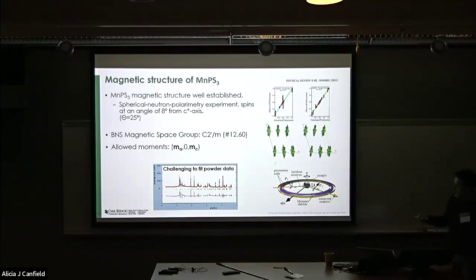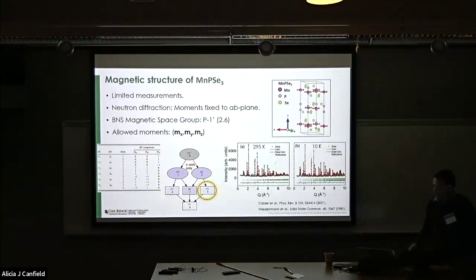So I'll point out here that this is some powder data that we collected on HB2A, the neutron diffraction instrument, where you can see in these 2D materials, you start to get these very distinct signatures, peak shapes of the 2-dimensional order that become very hard to fit. This is not a published fit. This is just to really show you the challenges you can get when you start to apply analysis to these data, and this is partly to motivate what I'm going to show, why we chose to do this MPDF technique, where you can start to really analyze the data in a better way. So that was MnPS3, with spins out of the plane.